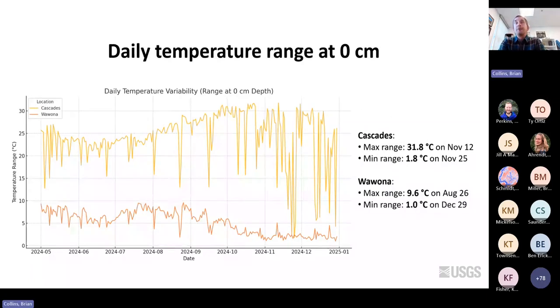When we look at the daily temperature ranges at the surface, we see very similar results. We have the maximum range on the south-facing slope in November, but also the minimum. But you can see from the graph that the temperature variability is mostly highest during the fall and winter months. While on the north-facing slope it is the contrary. We have quite stable variations during fall and winter, and we have the highest temperature variability during August, late summer.